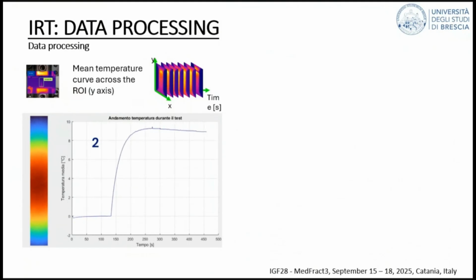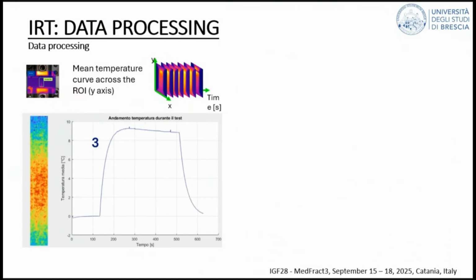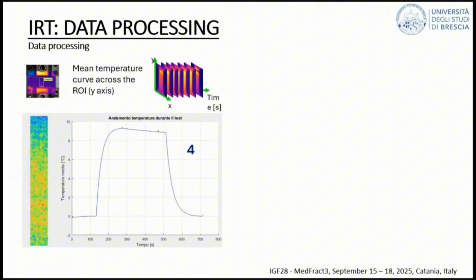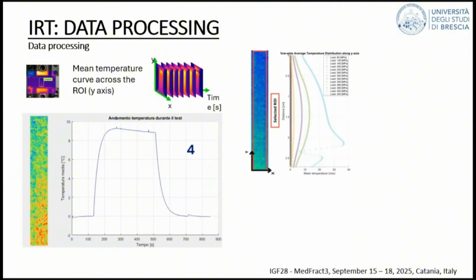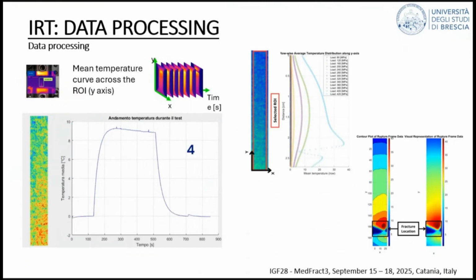So the first one is the application of the mean stress, then the application of the cyclic stress and its release, and finally the release of the mean stress. And in general, in the central region of the specimen, the temperature was rather uniform, except for, let's say, the final phase, when at high load level, we reach the failure. So in that case, you have here an example of the classic temperature distribution that we've got.